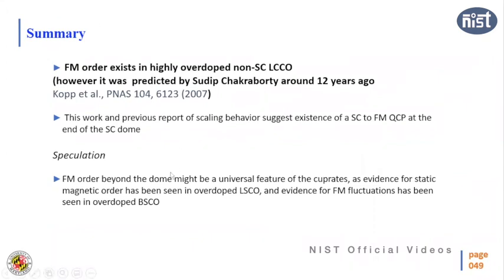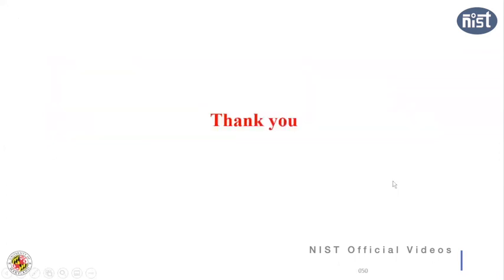So here is my summary. What we found beyond the superconducting dome, which was predicted 12 years ago by Sudip Chakraborty, there could be ferromagnetism. And we found there's a ferromagnetism as well as a quantum critical point. Now, if this is right, then one can speculate the origin of the demise of the superconductivity beyond the optimal doping. That means why Tc is decreasing when we go beyond the dome could be because of the ferromagnetism. Thank you.